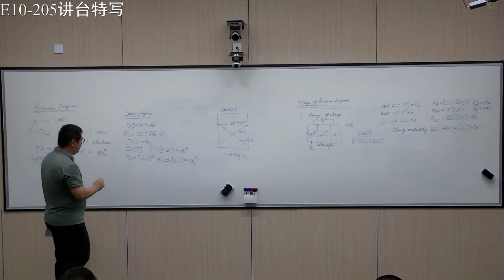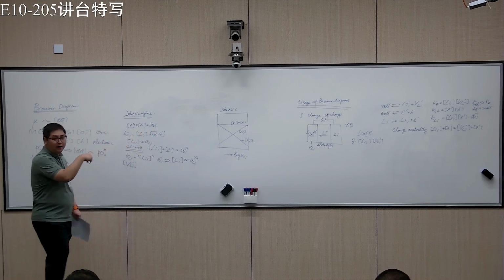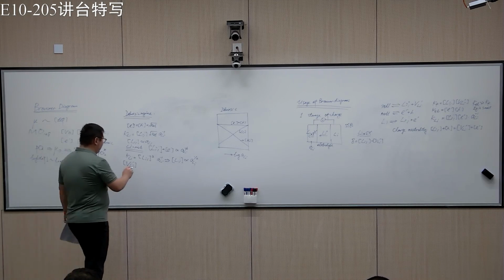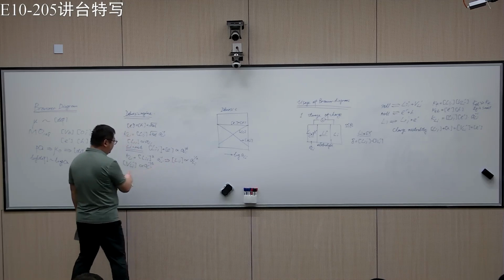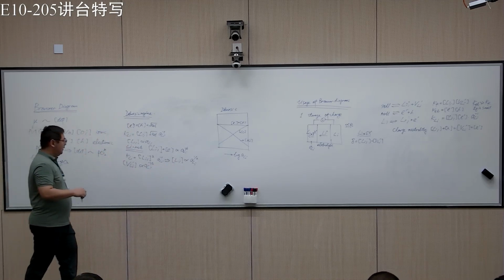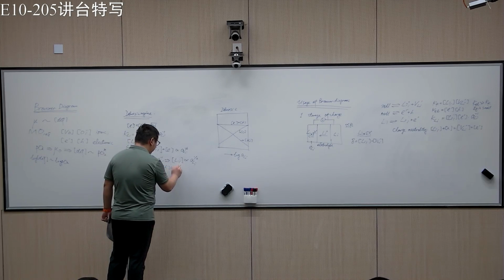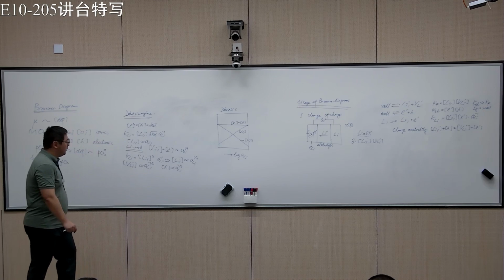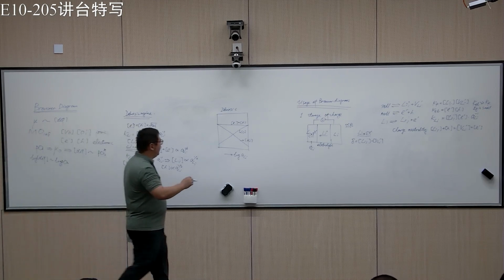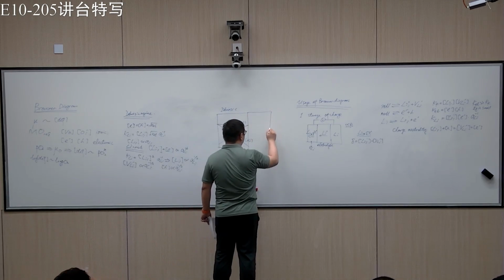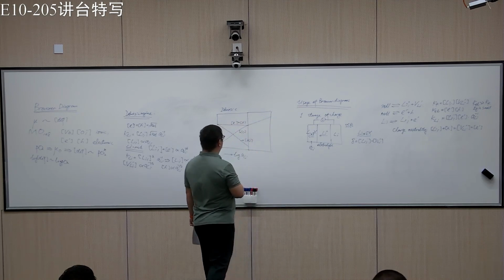Okay. So the electron is the same as this one. You can also solve for the vacancies from the Frenkel pair over there. We know that should be minus 1/2, because this times this should be a constant, right? And holes is also minus 1/2, because electrons times holes should be a constant. So we can put it into this Brouwer diagram.